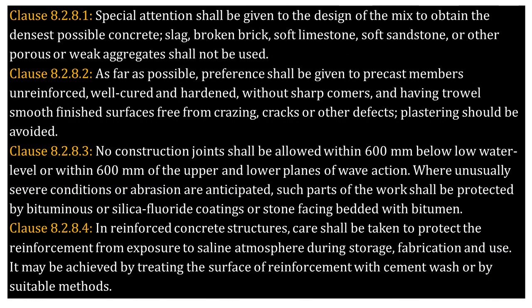In this slide, we'll delve into the subclauses of clause 8.2.8. These clauses are essential in ensuring the durability and longevity of concrete structures. Clause 8.2.8.1. Special attention shall be given to the design of the mix to obtain the densest possible concrete. Slag, broken brick, soft limestone, soft sandstone, or other porous or weak aggregates shall not be used.